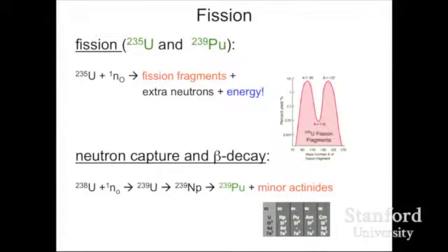These thermal neutrons can split uranium-235, but because its concentration in natural uranium is so low, in most nuclear fuels we enrich it to, say, 3 to 5 atomic percent so that we have enough uranium-235 to fission in the reactor.